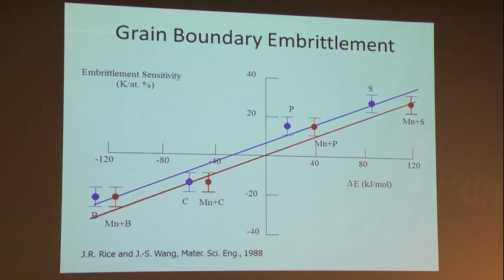One of the most ambitious problems was intergranular stress corrosion cracking due to environmental hydrogen interactions as affected by the prior segregation of embrittling segregants. And a very important contribution early on in the program was the work of Rice and Wang at Harvard, who developed a surface thermodynamic description of interfacial embrittlement by these components, where the embrittlement potency scales with the difference in the surface segregation energy between a free surface and a grain boundary.